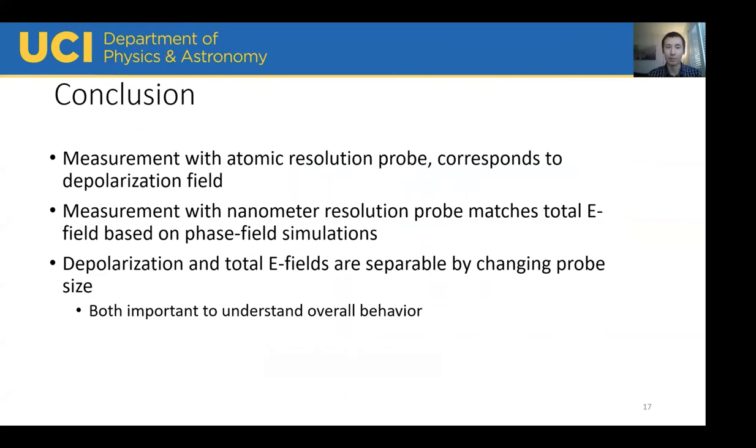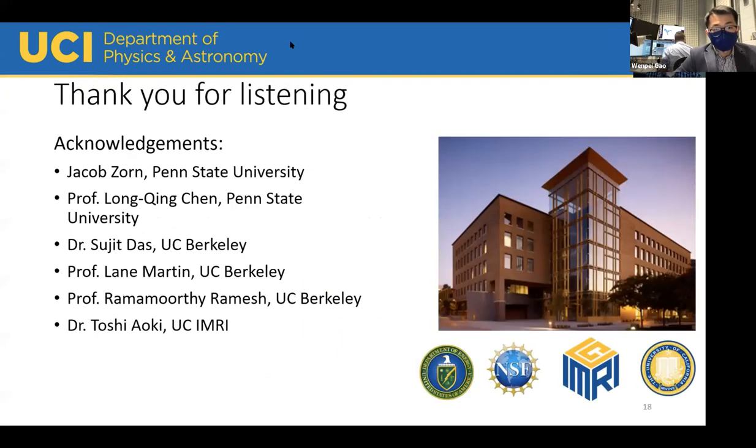In conclusion, we've shown that measurements of the electric field with an atomic resolution probe corresponds to the depolarization field in the ferroelectric. However, measurement with a nanometer resolution probe matches with the total electric field based on phase field simulations. So therefore, the depolarization field and the total electric field are separable by changing the probe size, and both are important for understanding overall behavior of the ferroelectric. I'd like to thank you for listening, and thank my collaborators for the help from this work. Thank you.